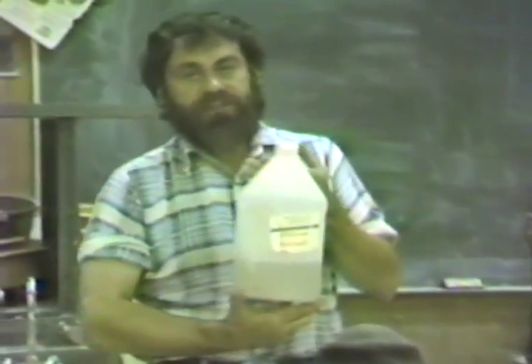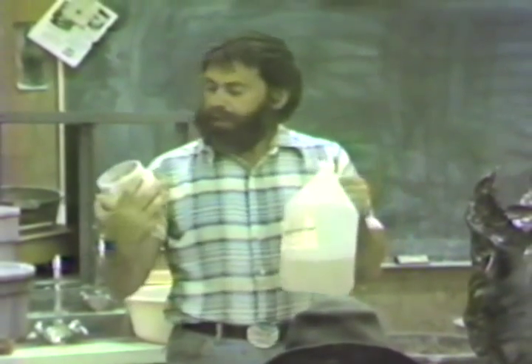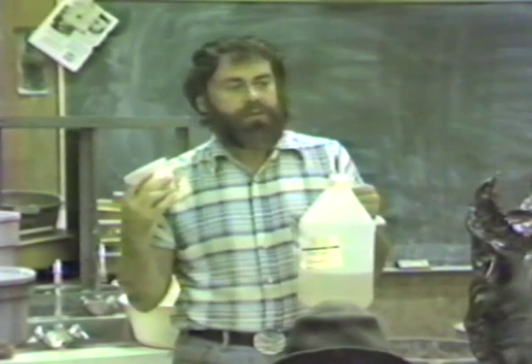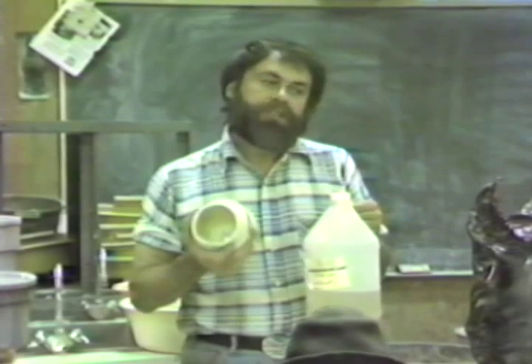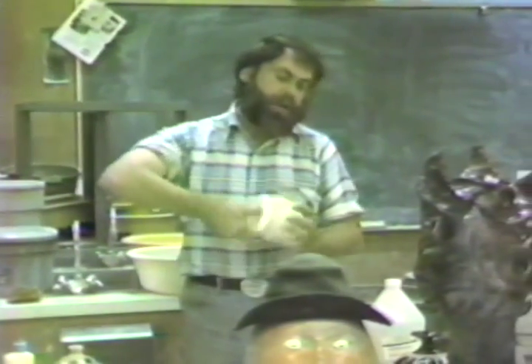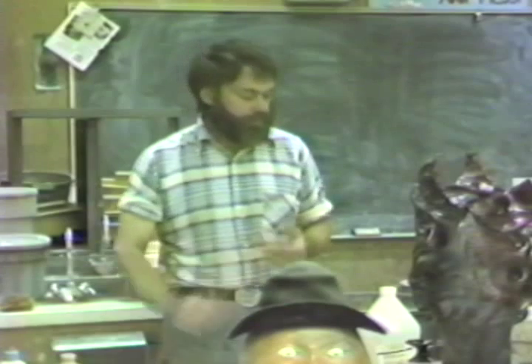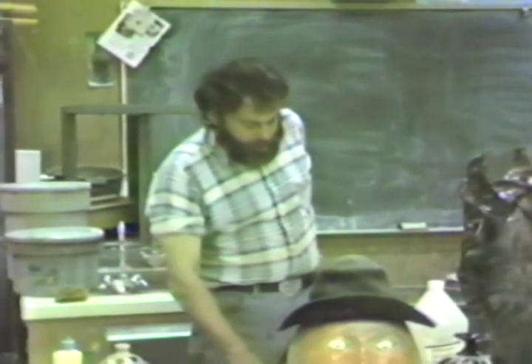Another one is the sodium silicate, which is basically a thinner solution of this product. The sodium silicate, you can get into very minute cracks, while this, which has clay body mixed into it, porcelain, won't get into the minute little cracks. So it's a toss-up of which one you want to use on some pots that have a crack that's in between those areas. And if there's ever any question in your mind, then come and talk to me and I'll try to help you make a decision on which product to use. Okay,